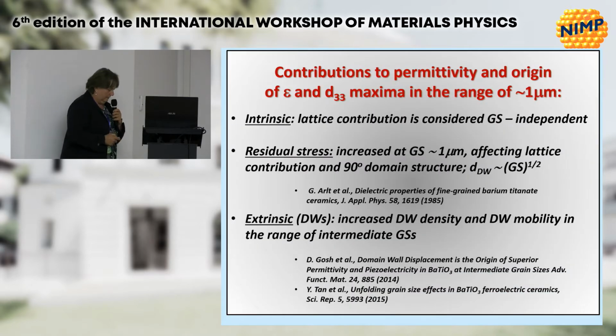Anyway, as interpretation for the contributions to this maximum, there are some quite old explanations and some that were recently accepted to be the final, the definitive explanation for this behavior. First of all, the intrinsic contribution is considered to be grain size independent. So no reasons to have a maximum according to the lattice were found by many experiments.